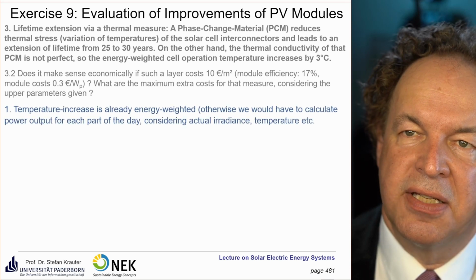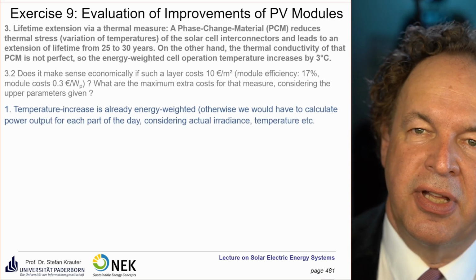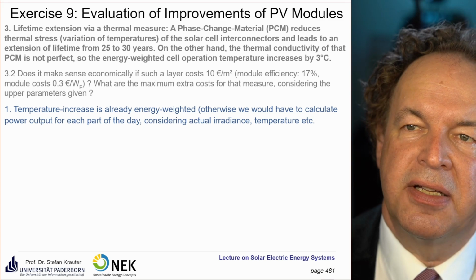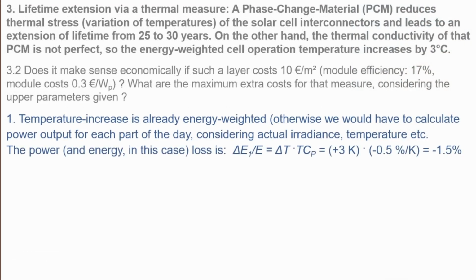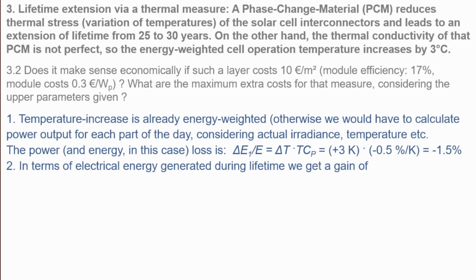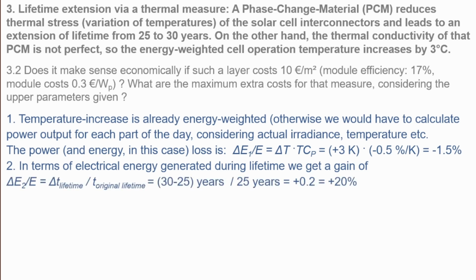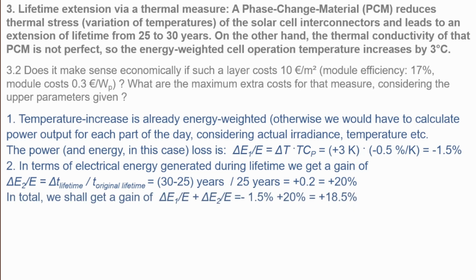So let's do an economic evaluation. Temperature increase is already energy weighted. We have here the power, and the energy is decreased by minus 1.5%. But we got an extension of lifetime, which is 5 years. So instead of 25 years, we get 30 years. So that's a plus of 20%. So considering the additional thermal losses, in total we still got 18.5% in gain.